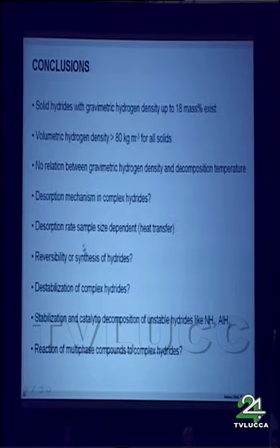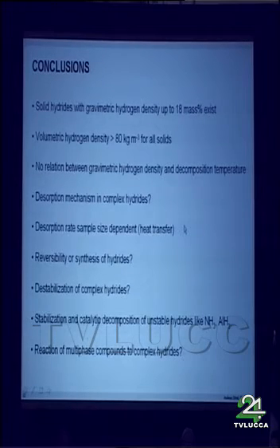The desorption rate is sample size dependent. It is, in most cases, and Gary Sandrock has published that more than 20 years ago. It's a problem of the heat transfer. So all these results which show a very high rate of hydrogen absorption or desorption are mainly done on small samples, and that's the reason why they have such high rates.